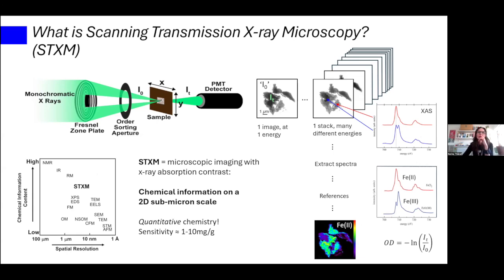Calcium, very sensitive. But other elements like sulfur, for instance, are less so. In comparison to other techniques that you may know, we can have a look at the spatial resolution versus the chemical content. And you see that we occupy a nice niche in the middle, where, of course, you can have better resolution with some of the techniques like STM or TEM even. But the chemical information that you can get from it is much better in STXM. On the other hand, IR, for instance, can give you quite good chemical information, but usually the resolution is not so good unless you do AFM-IR, but that's a different story. Right, so this is in a nutshell how you should think about STXM. It gives you chemical information on a 2D submicron scale. 3D is possible, but it's cumbersome.